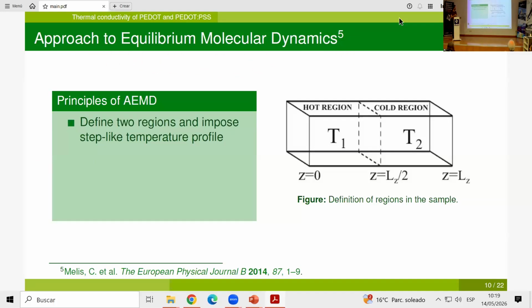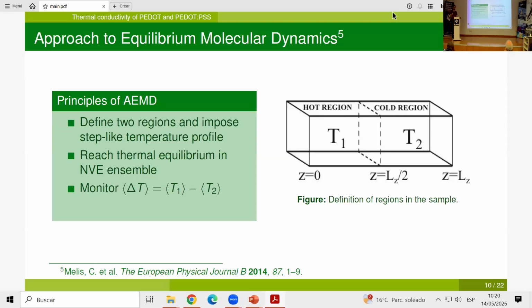This consists of creating a simulation box, dividing it into two halves, and setting a step-like temperature profile. For example, we set one half at 400 Kelvin and the other half at 200 Kelvin, creating a delta T of 200 Kelvin, and then let the system reach equilibrium. While it does, we monitor the average delta T, which is the difference between the average temperature of the two regions, and we extrapolate the lattice thermal conductivity from the exponential decay of the average delta T.